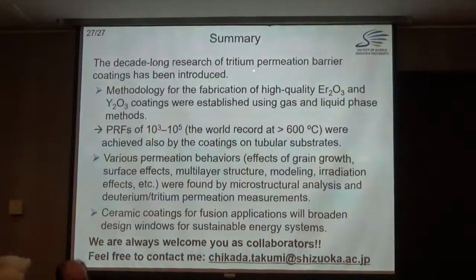The decade-long research of tritium permeation barrier coatings has been introduced. Methodology for the fabrication of high-quality erbium oxide and yttrium oxide coatings was established using gas and liquid phase methods. Permeation reduction factors of 1,000 to 100,000 were achieved, also by coatings on tubular substrates. Various permeation behaviors, such as the effects of grain growth, surface effects, multilayer structure, modeling, and irradiation effects, were found by microstructural analysis and tritium permeation tests. And ceramic coatings for fusion applications will broaden design windows for sustainable energy systems.